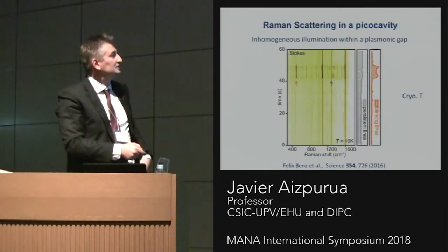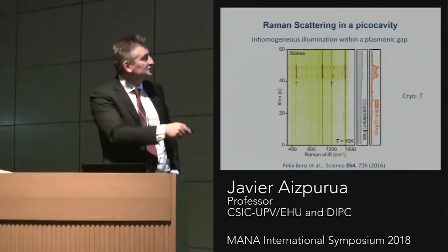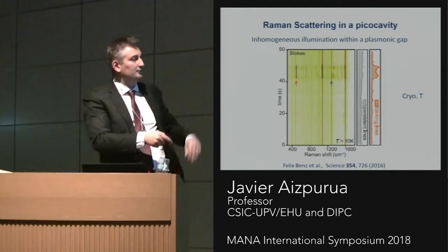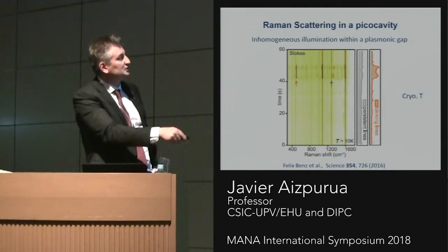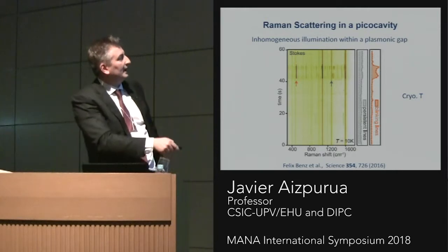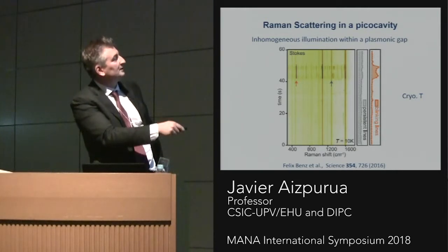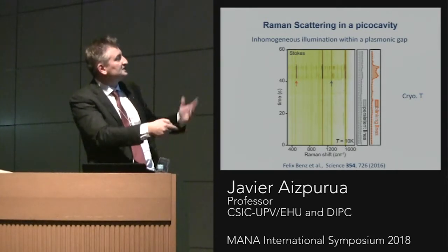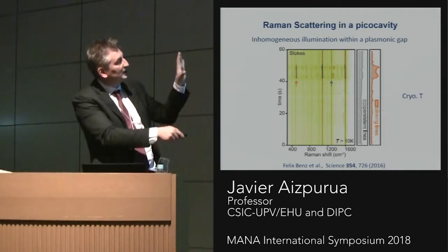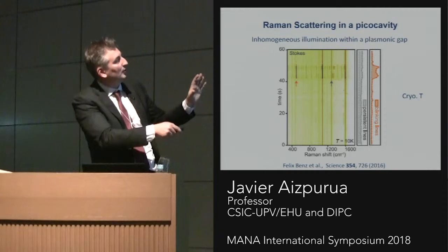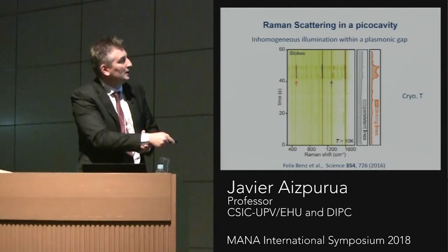So in these situations, Jeremy Baumberg in Cambridge did this experiment on this kind of nanoparticle-on-a-mirror situation. This is the Raman of such a situation, this biphenyl, and he recorded the Raman, the vibrational fingerprints of these molecules in this cavity along a couple of minutes, right? And we could distinguish 2 types of Raman vibrations.